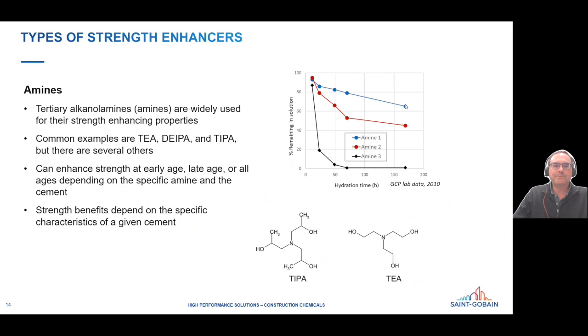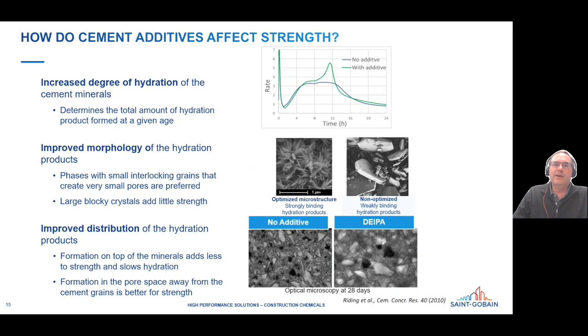So then what are these additives actually doing to affect the strength? Well, there's a few different things that they do. One of them is simply to increase the degree of hydration of some of the cement minerals, particularly the ferrite and aluminate phases. The degree of hydration could be improved, and you can see an effect in a calorimetry curve here. You can see this on the green curve, this peak here that appears when you're using the quality improver.